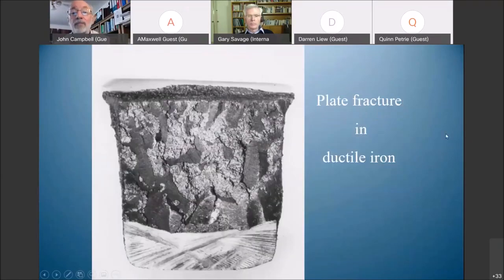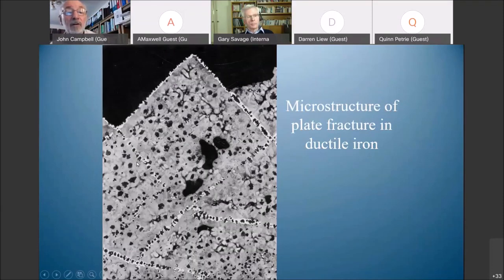And here's cast iron with so-called plate fracture of ductile iron. I mean, this should never happen, that we get brittle fracture of grains like this in ductile iron. But it happens because of bifilms. And when we slice the structure and look at it, these are the lines of the bifilms. I mean, this is just an amazing structure, which you'd have no hope of explaining without some knowledge of bifilms.